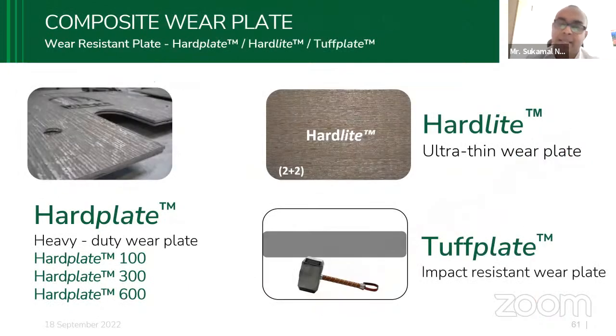Composite plate. This is the one which is used almost everywhere in the cement industry. I just talked about this, called a hard plate, which basically enhances the life of the component by protecting it from all kinds of erosion, sometimes even corrosion. There are 3 types of hard plates: 100, 300, and 600. Depending on the application, the life enhancement the customer wants, and the criticality, we provide the solutions.